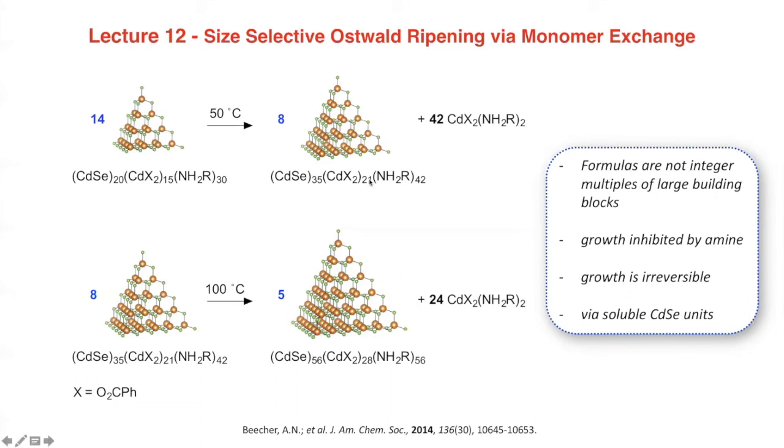They also have the expected metal-rich formula of the surface chemistry that we've talked about, metal enrichment, and really these pyramids have pure cadmium termination. So all their facets are terminated with cadmium, and they have this number of ligands that bind. This guess of the formula, this number of ligands, corresponds to the number of dangling bonds. So each of these pyramids achieves a fully saturated type of structure.